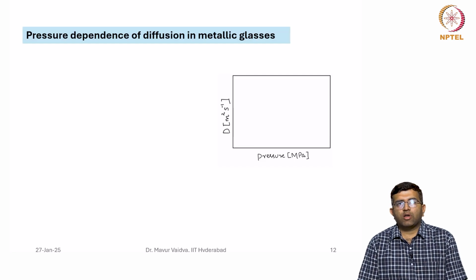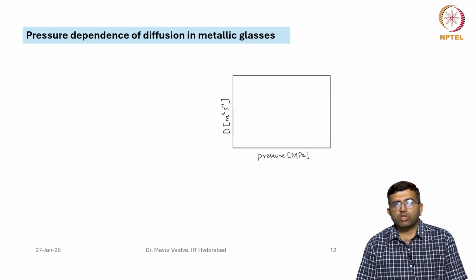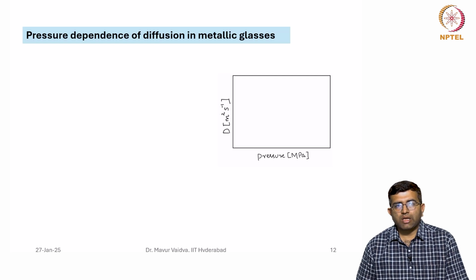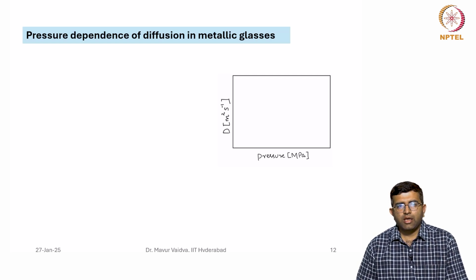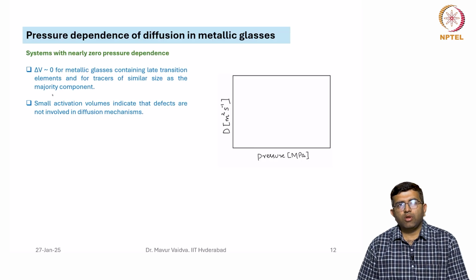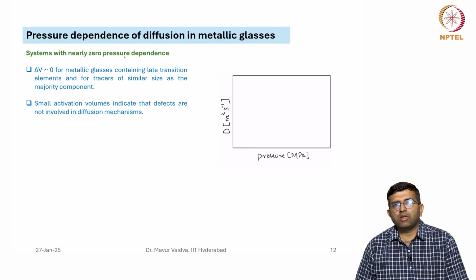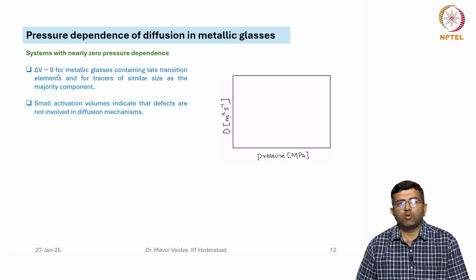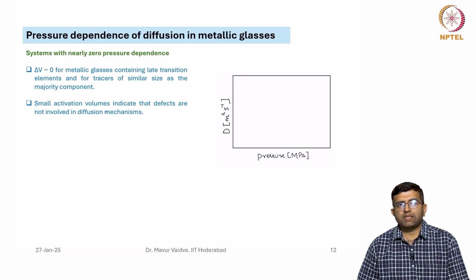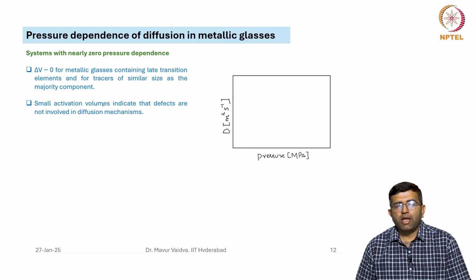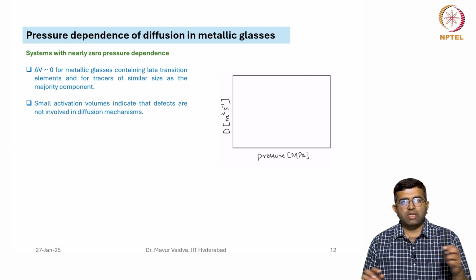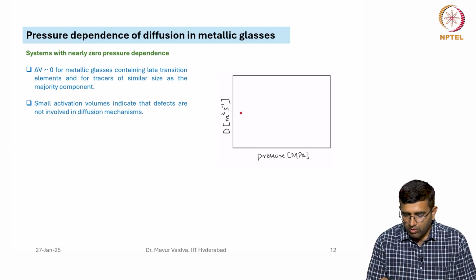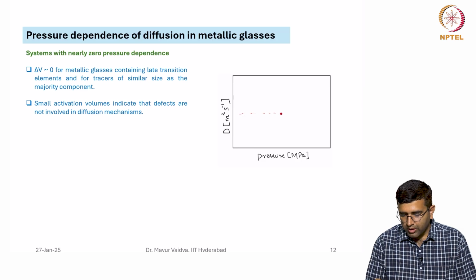Finally, let us also have a couple of words about the pressure dependence of diffusion in metallic glasses. The pressure dependence of metallic glasses has been studied to some extent. Two types of pressure dependence have been observed. One is systems with nearly zero pressure dependence, where the activation volume is almost equal to 0. This is true typically for metallic glasses containing late transition elements, where the tracers are of similar size as the majority component. Small activation volumes basically mean that if you plot D versus P, it will almost be like a horizontal line.